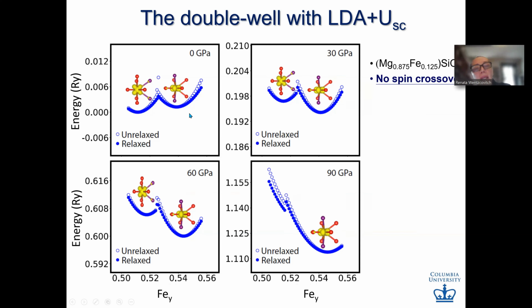As I'm saying, like in the high spin, low spin case, you have quadratic energy surfaces here, and the ions are separate, so they can coexist in a situation like this. That's what the experimentalists are seeing in Mössbauer: two kinds of high spin iron on different sites with minority electrons in different orbitals. As you change pressure, the high pressure, high quadrupole splitting state becomes more stable than the low pressure state, and eventually the low pressure state goes away. But this is not a spin state change. It's a change in orbital occupancy with pressure.